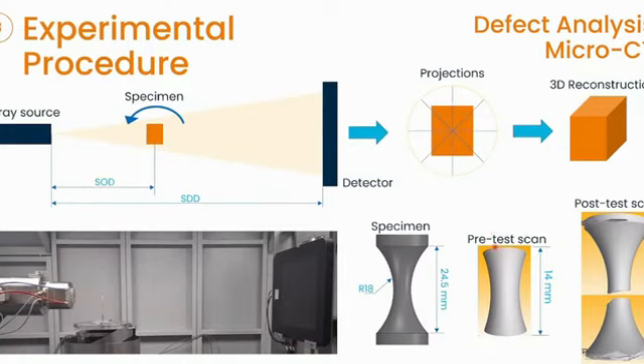Each specimen will be scanned before the ultrasound tensile testing for defect analysis purposes, and then the pieces after the ultrasound tensile testing will also be scanned, so they can be overlapped with the original scan to identify which defects were present in the failure zone.